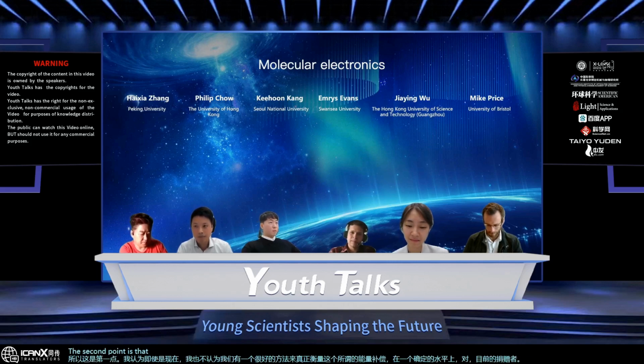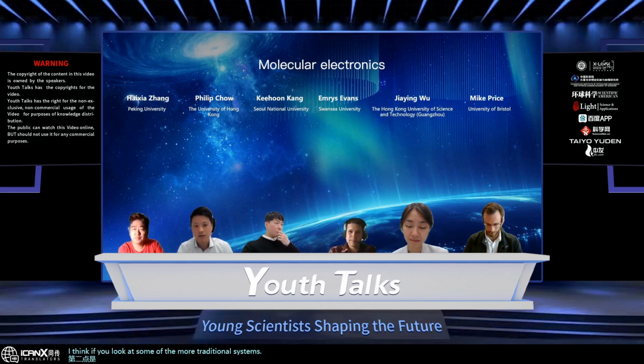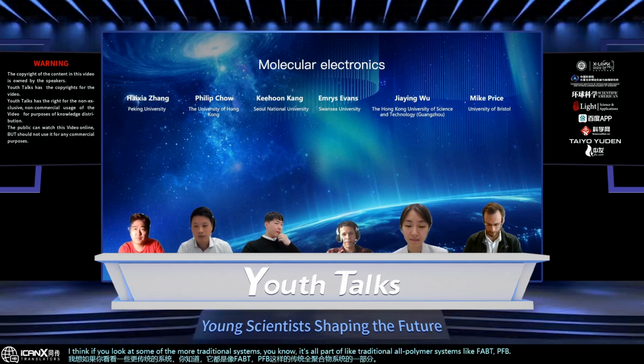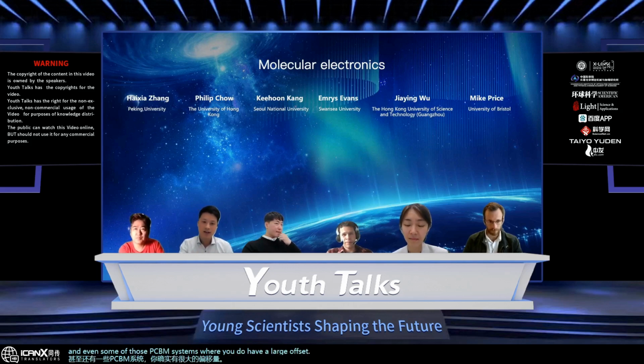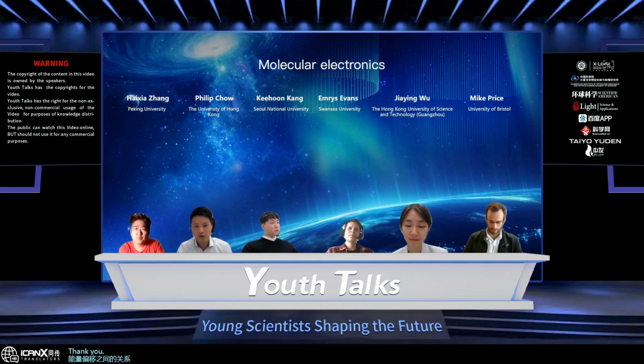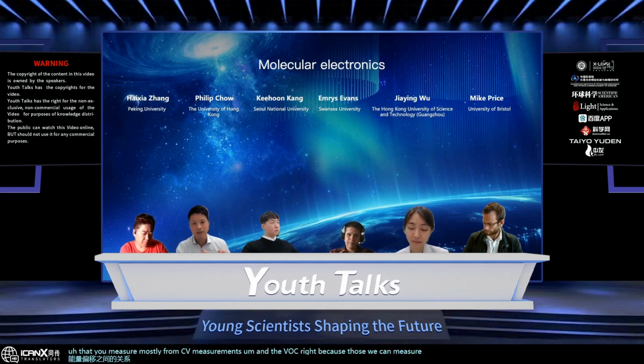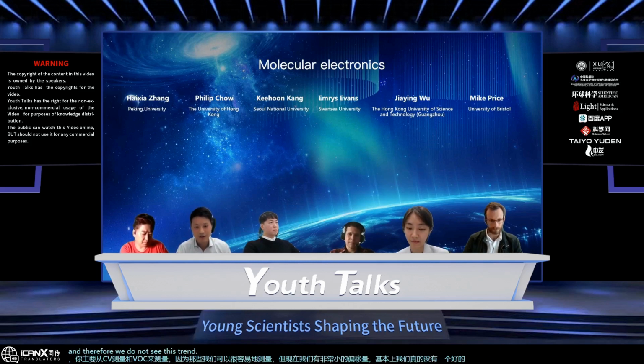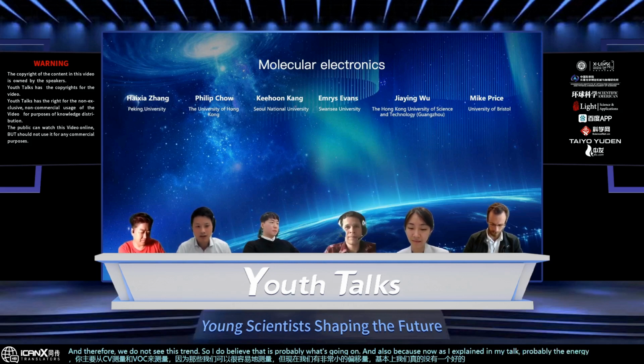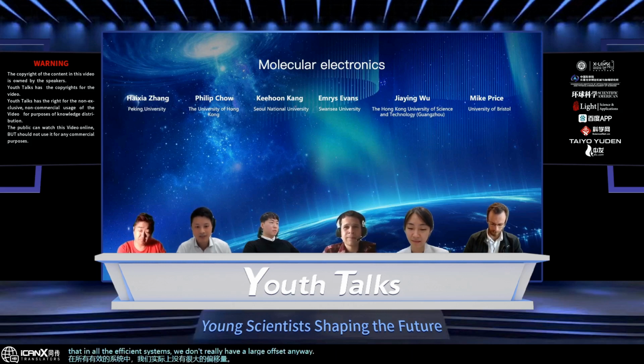The second point is that if you look at some of the more traditional systems, the traditional all-polymer systems like F8BT, PFB, and even some of those PCBM systems where you do have a large offset, then you can clearly fit a relationship between the energy offset that you measure mostly from CV measurements and the VOC, because those we can measure easily. But now we have very small offsets, and we don't really have a good way of measuring them, and therefore we do not see this trend. I do believe that is probably what's going on, and also, as I explained in my talk, the energy offset is probably already very small in all the efficient systems. We don't really have a large offset anyway.